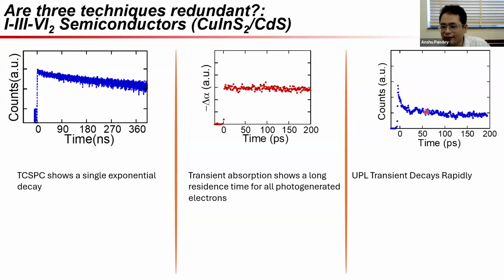Okay. It's something interesting actually, because this immediately starts contradicting. So this is a very leading and nice question, so thank you for that, because we get an exponential decay here. We get a very nice exponential-like decay over here. But over here, we see a very, very ill-behaved character, because this is showing a fast decay and then a flat line. So this is firstly a big surprise, because other techniques would say nothing of this sort should be happening.